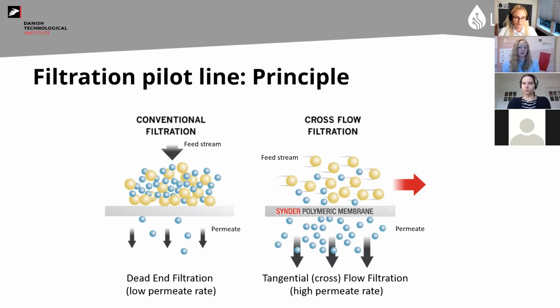And also when you come up to bigger amounts, it's a little bit more difficult to work with. So other people can use conventional filtration, but here you also have the issue that the particles can stick in the filter, or it can clog the filter basically. So what we use instead is the cross-flow filtration system, where, as you can see, you have the feed stream going aside the filter, and then we add a small pressure to it, so we actually push out the permeate through the filter, and the nanoparticles would just pass through.